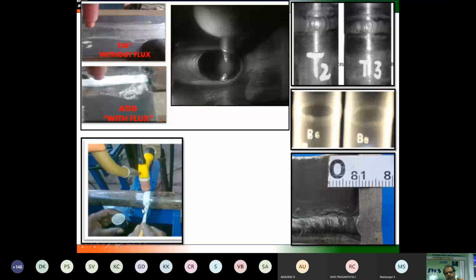What you are seeing are the radiographic images of the weld showing the uniform penetration. What we achieved is shown in a cut section of the weld. So penetration level is ensured up to 7 mm wall thickness. It's not at all a problem. Please watch the video here.